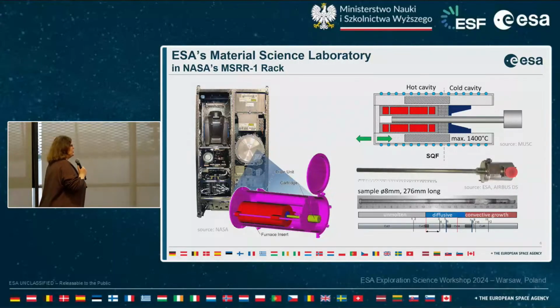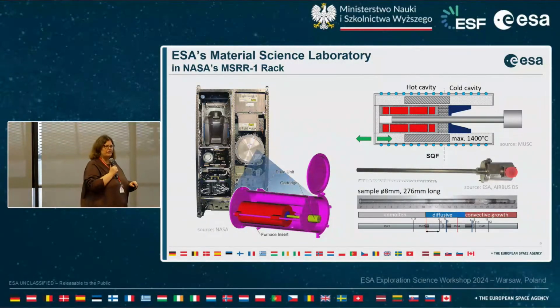As I said at the beginning of my talk, we are interested in studying the influence of fluid flow. We use an additional feature of MSL. Within these furnace facilities, a coil system is implemented, which induces a rotating magnetic field, so that in principle it acts like an electromagnetic stirrer. So we induce, during the solidification process, controlled fluid flow conditions. This enables us to solidify one and the same sample, first part under diffusive mass transport conditions in microgravity, and the second half, more or less, under controlled convective conditions, so that we can compare the microstructures in one and the same sample, fluid flow or no fluid flow.